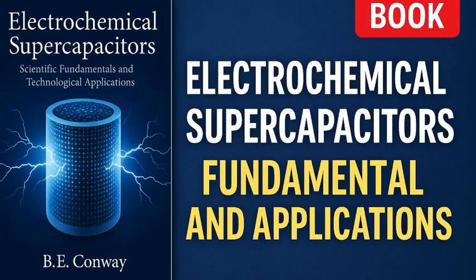Researchers try to mitigate this by using composite designs, for example, polymer coated on carbon fibers. The carbon gives a scaffold that supports the polymer and maybe reduces strain. Polymers often have lower electrical conductivity than carbon, so a polymer electrode might need a conductive additive or very thin configuration to ensure fast electron transport. All that said, polymers are promising for applications where energy density is more crucial than ultra long cycle life or extreme power. They can potentially store more charge in a given volume than carbon, since they can have battery-like multi-electron redox,